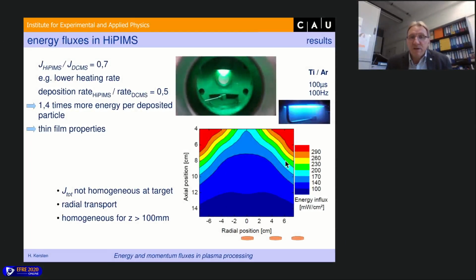Then we map the area, as you can see here, and here is near the target. It is very inhomogeneous, as you would expect, but at an axial position of about 10 centimeters from the target, there is a very homogeneous area of the energy influx, and that means also a very homogeneous deposition. So the substrates for thin film growth in this HiPIMS process should be positioned somewhere here.